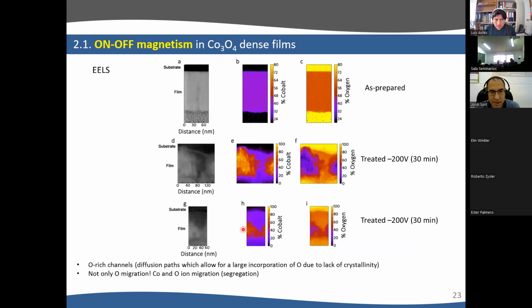Okay. This is better seen by EELS. The first row here is the as-prepared state. You can see that the contrast is homogeneous and it corresponds to about 40% cobalt, 60% oxygen. So this is Co3O4 more or less. But when we apply voltage, there are channels, basically, so regions where the amount of cobalt is depleted, and we have enrichment in oxygen. And this seems to correlate a little maybe with the columnar growth of the film. Because it was columnar, maybe the oxygen migration takes place preferentially along grain boundaries.